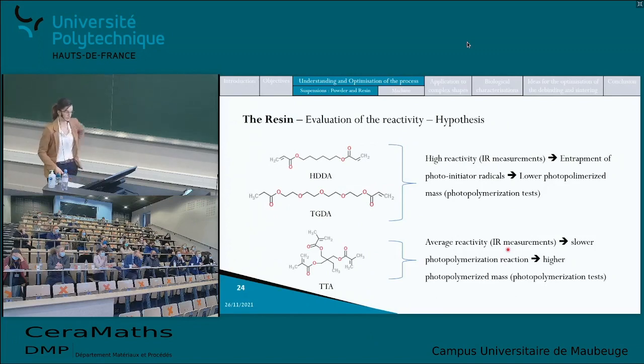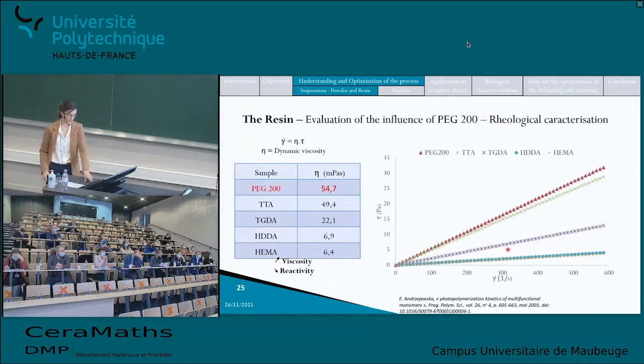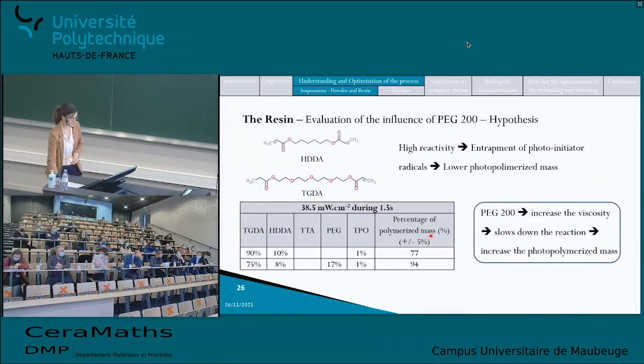However, what about the polyethylene glycol 200? Well, I measured the viscosity of the polyethylene glycol 200 and I realized that its viscosity was above the viscosity of all the other monomers, meaning that the increase of viscosity of the resin will decrease its reactivity and therefore slow down the reaction, avoiding the entrapment of photoinitiator radicals in the network and therefore increasing the photopolymerized mass. So that was how I was able to explain the results obtained during the first photopolymerization tests.